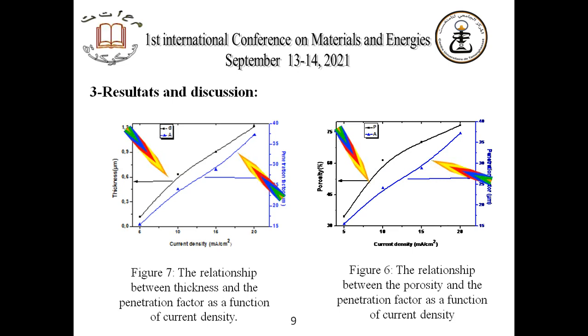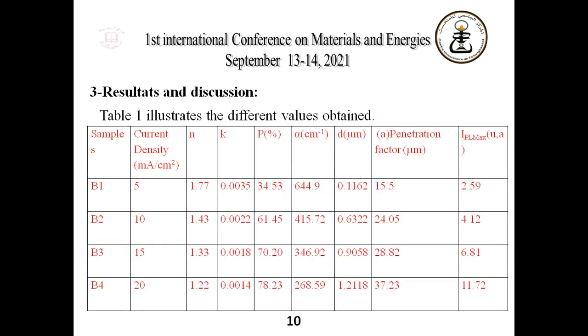In Figures 6 and 7, the calculation of the absorption coefficient allows us to plot the variation of the penetration factor with the porosity as a function of the current density. The figures show that this factor is an increasing function with the current density. Table 1 illustrates the different values obtained in this experimental work.